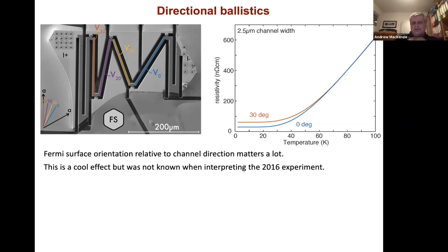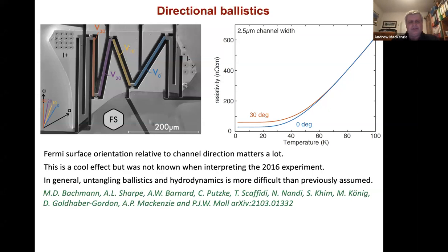I think it's also telling you something quite interesting, because ours was one of a number of experiments that came out in 2016 about hydrodynamic transport. And in each of those cases, the more we as a field have thought about non-local transport beyond the Boltzmann approximation, untangling the effects of ballistic as opposed to hydrodynamic transport has proved to be a lot more difficult than we all assumed it would be before we started trying. So in the broadest sense, that's an example of that. I'm going to guess that by the time we've sorted this out completely, we may see some very small viscous contribution to the observations we're making, but most of it will in the end be due to ballistics.